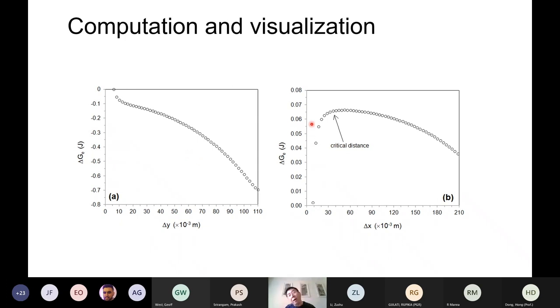However, if they are in a horizontal way, if they are very close, then you see when they separate, the free energy increases. That means the free energy will try to put them together rather than separate them. But after a critical distance, the electric current will try to separate those inclusions. In other words, the electric current tries to prevent them from agglomeration if the critical distance is that way.